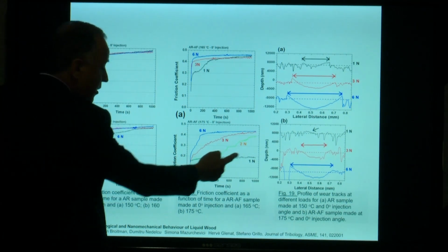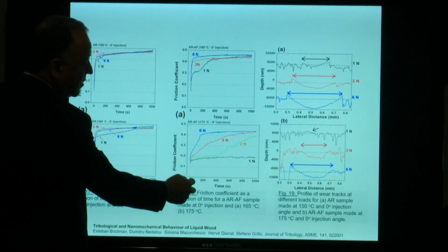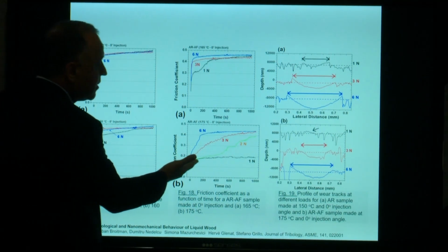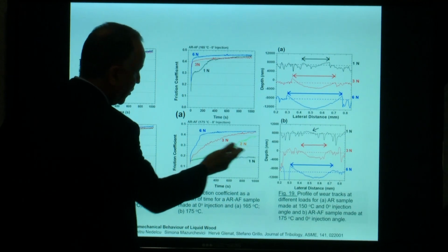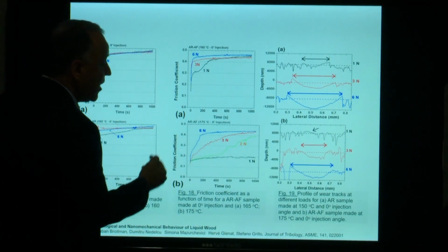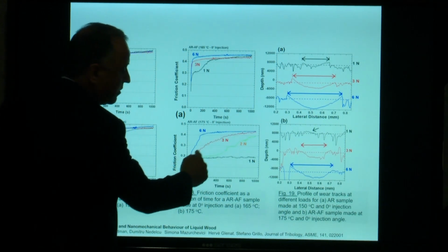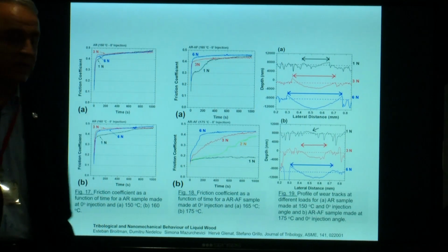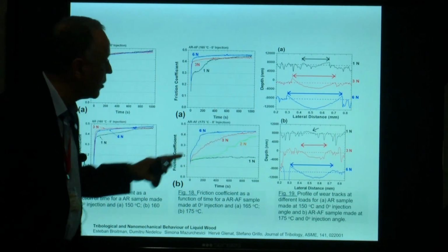For 1 Newton, you can see during 20 seconds around 0.15, increasing not suddenly up to 0.2. But when we change the loading force to 3 Newton, you can see the total behavior of the friction coefficient changes, and also for the 6 Newton.